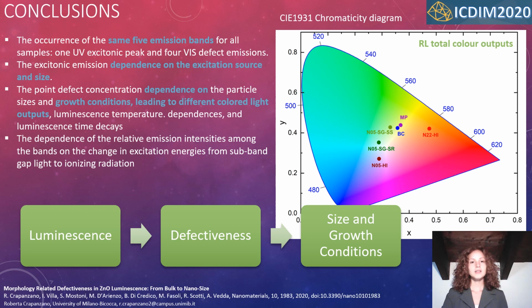In conclusion, this work highlighted the occurrence of a UV excitonic peak accompanied by 4 defect-related visible bands throughout several zinc oxide specimens with different morphologies, unveiling the presence of the same defect species. Anyway, the relative concentration of the defects varies with the size and the growth condition, leading to a different colored light output, as the chromaticity diagram shows. Each point of the diagram represents the overall shade of color that zinc oxide specimens emit under X-ray excitation.